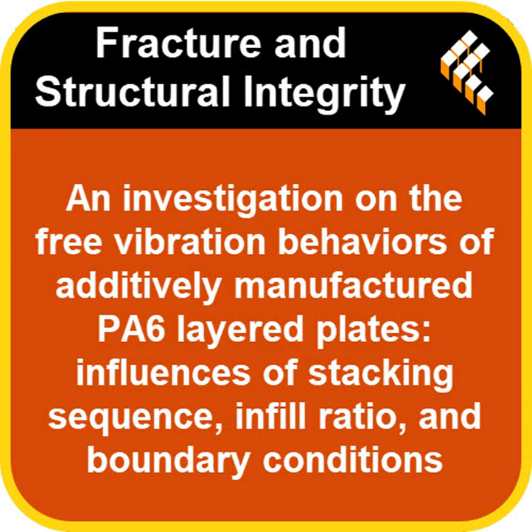It really comes down to this interplay between stiffness and mass distribution, particularly how it affects the plate's ability to resist bending, its flexural rigidity. Okay. So when you place those stiff, high infill 100% layers on the surface, they're furthest away from the neutral bending axis, the center plane. Right. They become incredibly effective at resisting bending, like an I-beam where the flanges do most of the work. Okay, I see the analogy. So this significant boost in structural stiffness, in flexural rigidity, has a more dominant effect on raising the natural frequency than the overall mass of the part does. So stiffness on the outside wins for higher frequencies. For raising natural frequencies in these bending modes, yes, it seems so in this study.